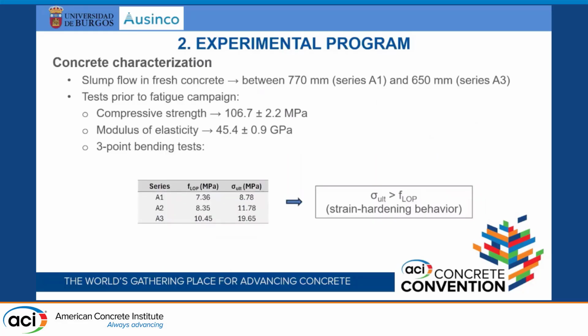And then, before the fatigue test, we have characterized these 3 types of concrete, A1, A2, and A3. Here, maybe the most relevant is the compressive strength of more than 100 megapascals after 1 year, and obviously the 3-point bending test to characterize the static flexural behavior. This is the stress corresponding to the limit of proportionality, f_LOP, which is more or less the first crack strength, and here the ultimate strength, which is the maximum equivalent stress that the specimens reach along all the tests.